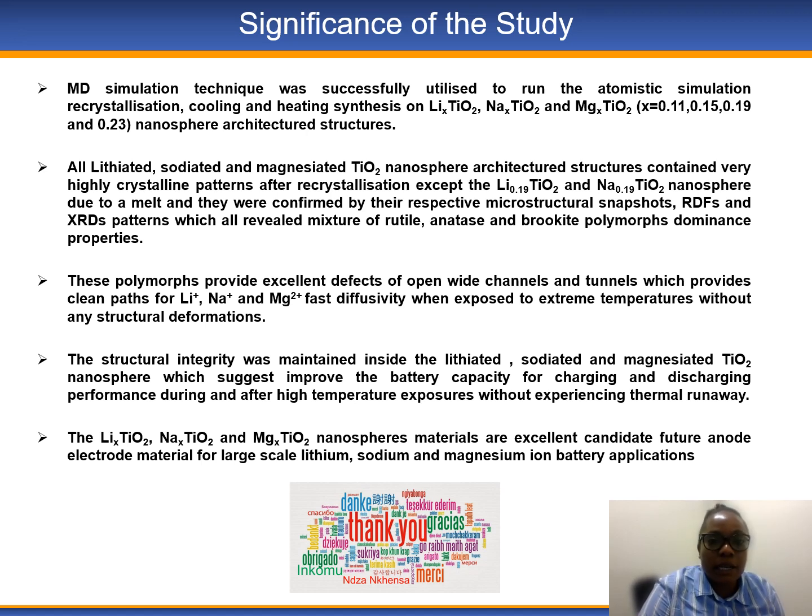Molecular dynamics simulation technique was successfully utilized to run the atomistic recrystallization, cooling, and heating on our lithiated, sodiated, magnesiated titanium dioxide nanosphere. This system shows to be a very smart material because it contains highly crystalline patterns after all recrystallization. However, the systems with 0.19 lithium and sodium were shown to have melted, as shown by their respective melted structure, and the ones that managed to recrystallize were confirmed by their respective microstructural snapshots.